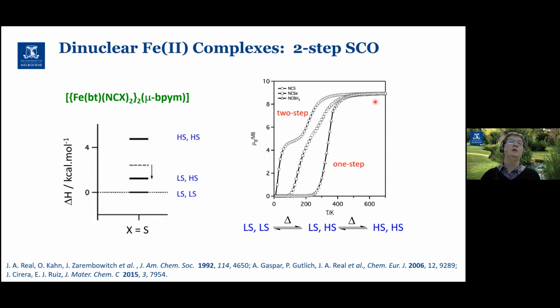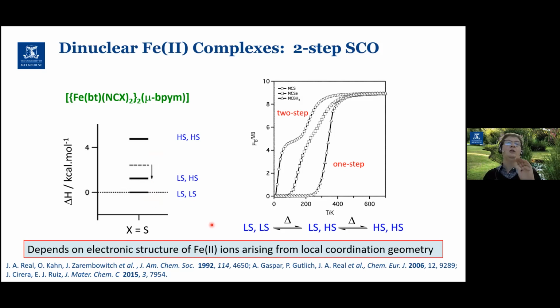So that's been well understood, I think, for quite a while in terms of the energetics that's required to achieve that two-step transition. Essentially, to get a two-step transition, you need the mixed spin state to be lower in energy than the halfway point between the low spin and the high spin form. So that's been well known for quite a while. I think what's been a bit less clear is what actually causes that low spin, high spin, mixed spin state to be lower, less than halfway in energy.